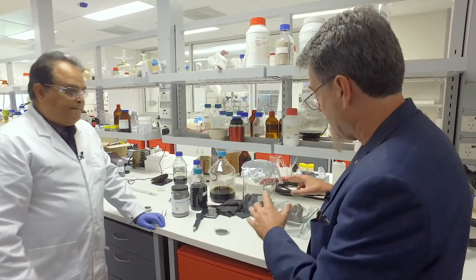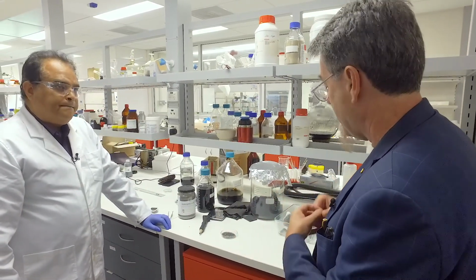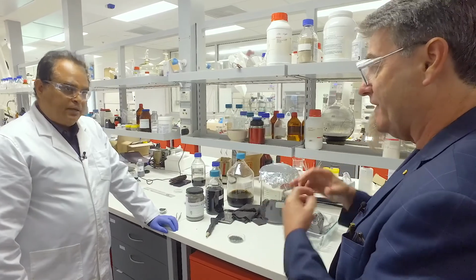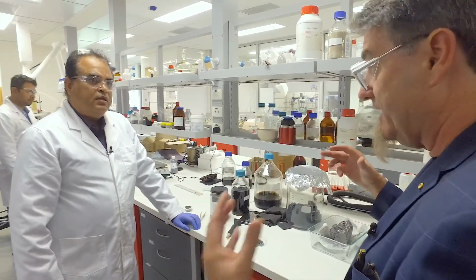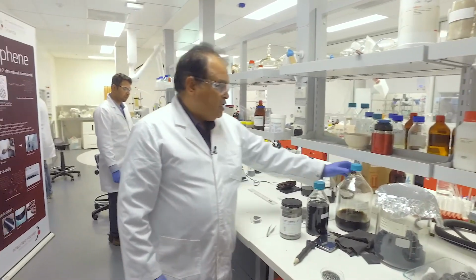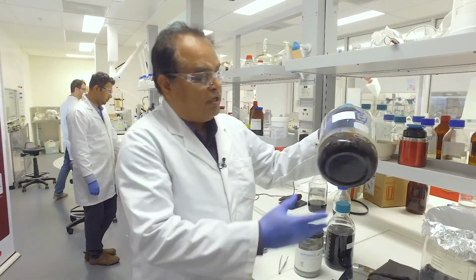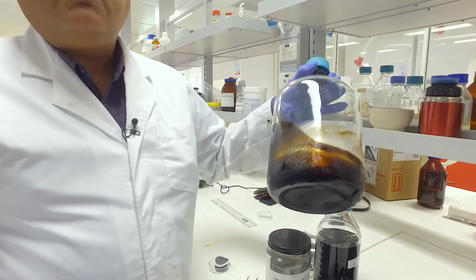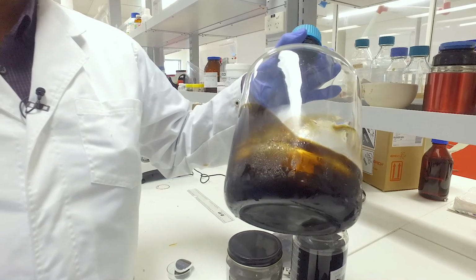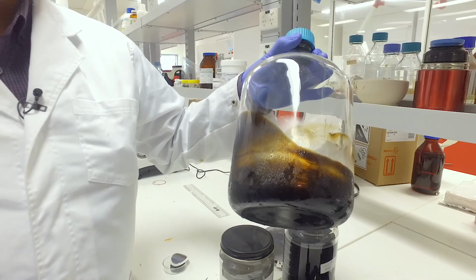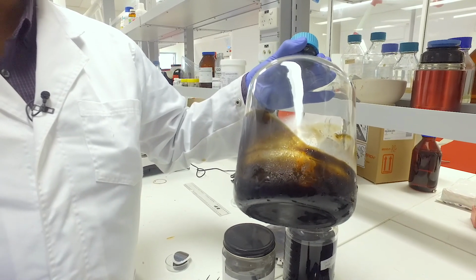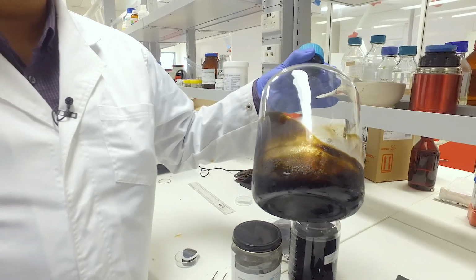Right, so now we've got this thermally expanded material and we're going to chemically oxidize it. And does that cause it to break up into the individual sheets? Absolutely. This is what we have been getting. This is the graphene oxide, which is a very large sheet of graphene oxide, around 50 to 70 micron sheet, which is having a unique property forming the liquid crystalline nature of the material as well.